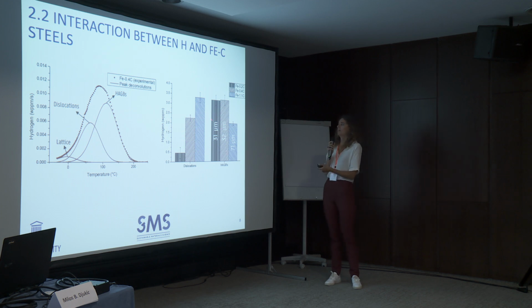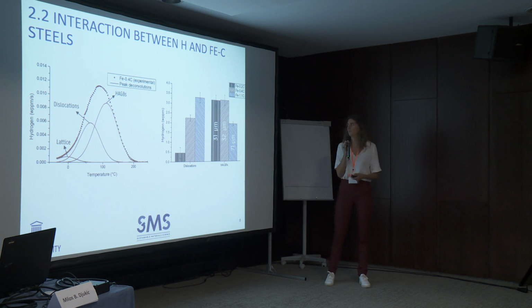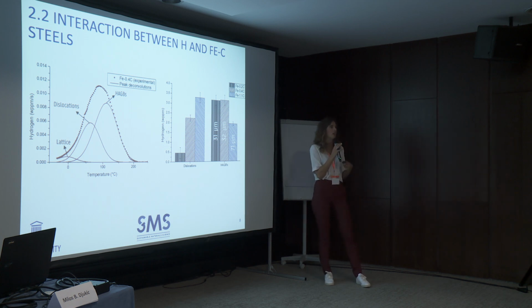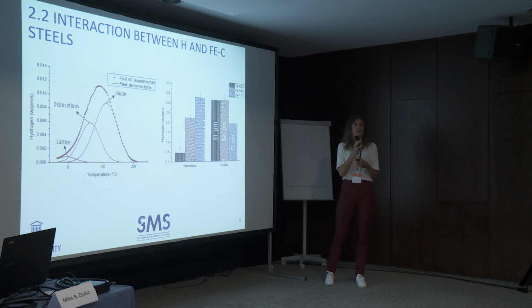The amount of hydrogen trapped at the high-angle grain boundaries mainly depends on the parent grain size. The higher the parent grain size, the less hydrogen can be trapped there. This is because the amount of high-angle grain boundaries is inversely proportional with the parent grain size.